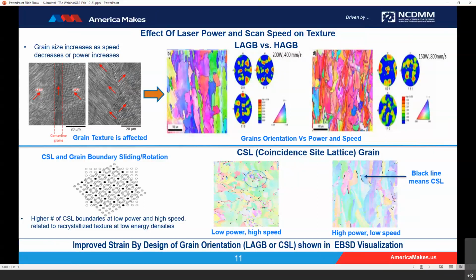In this case, not only are we seeing grain angles, but we're also seeing the impact of power and speed on textures. In the lower right-hand side, the same capability is accessible for coincident site lattice grains, where the coincident site lattice is impacted by variations in power and speed. Here, the small black lines correspond to the actual coincident site lattice grains. And as you can see on the lower left, grain boundary sliding and rotation also can occur at multiple levels. The higher number of CSL boundaries at low power and high speed are related to recrystallized texture at low energy densities. Ultimately, improved strain by design of grain orientation is shown by EBSD visualization.